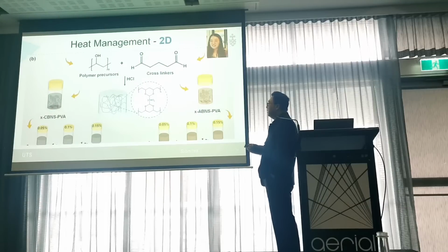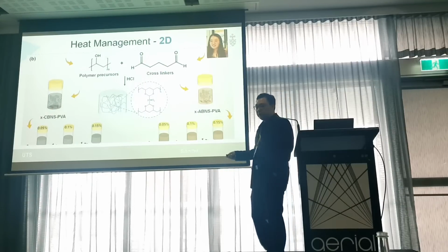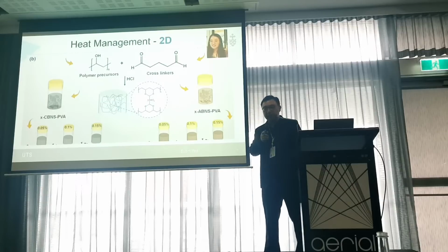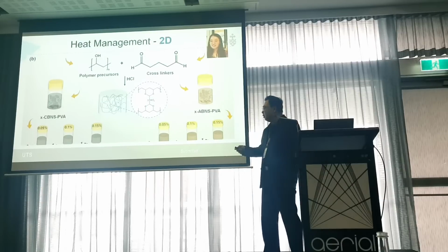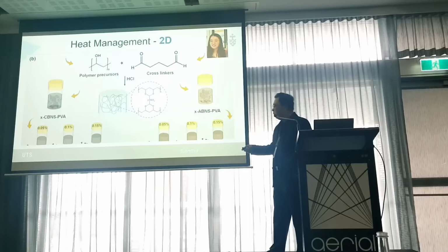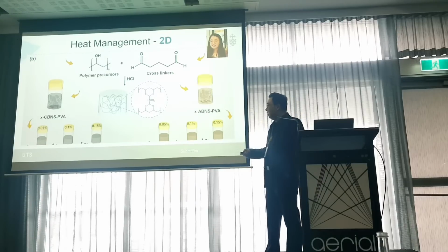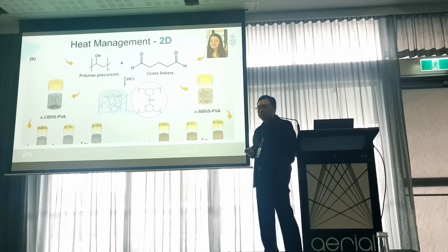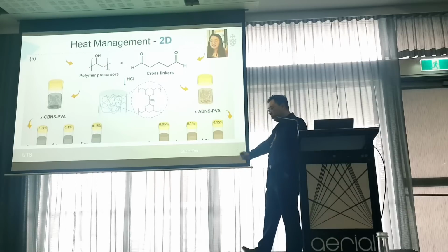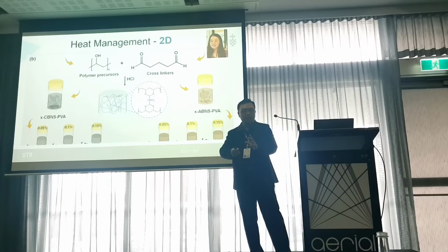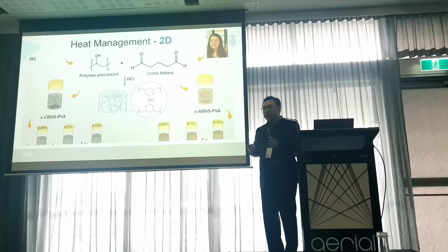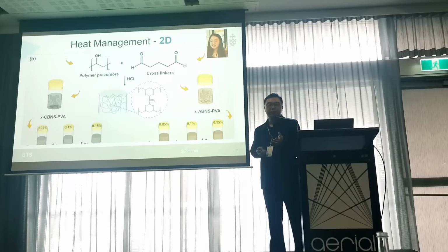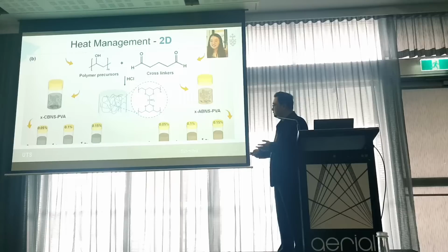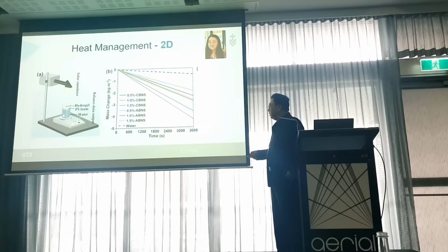And then we use the same polyvinyl alcohol as a polymer matrix, adding a very tiny amount, a trace amount like 0.1 weight% or 0.05 weight% of 2D materials as the photothermal materials into the hydrogels. Through the same cross-linking and freeze-thaw process, we successfully prepared the PVA hydrogels with 2D photothermal materials, with different types of photothermal material. Then we use the same setup to test the water evaporation rate